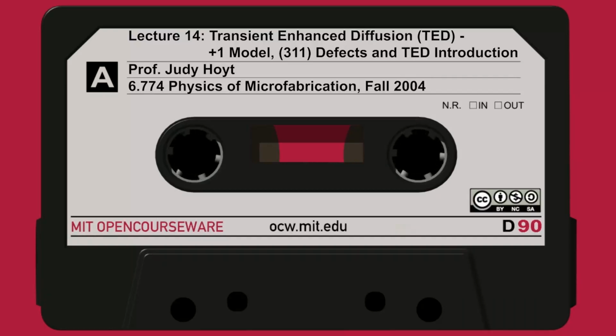This is actual data. And now look at the boron profile, the open triangles. For the exact same anneal, when you implanted the emitter, the open triangles have broadened. That profile is completely broadened. The peak concentration is dropped, and now you have these large wings. Well, there's a lot of enhanced boron diffusion. This is TED. And this makes the device essentially inoperable. The HBT doesn't work when it looks like this.